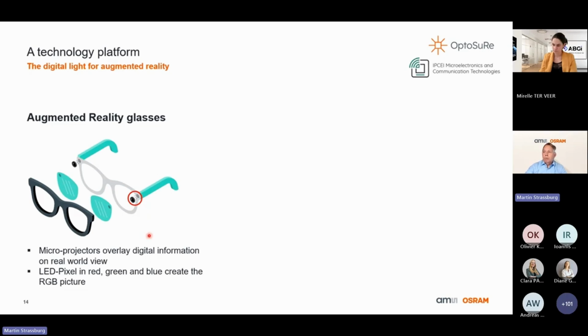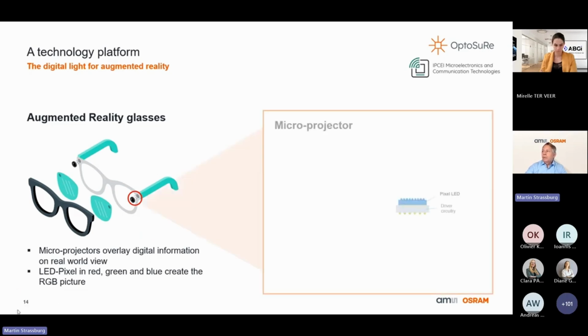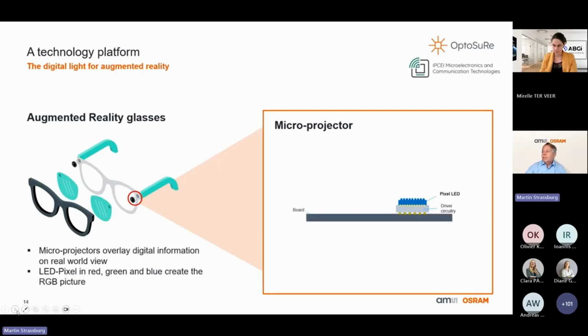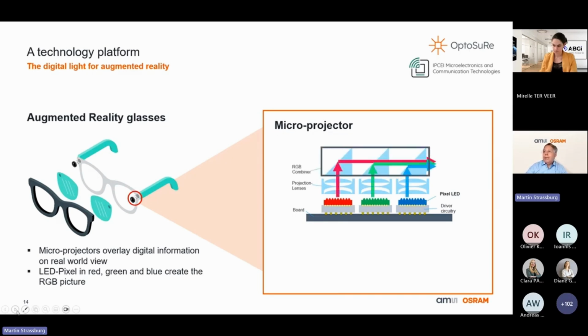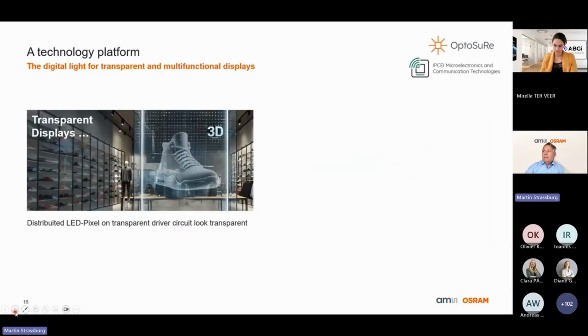The RGB projection is considered. And therefore we would use a micro projector. You see here again the micropixelated LED. Now 25,000 pixels are not sufficient anymore. Here we talk rather about 1 million pixels and smaller pixels. And to get the RGB, everything is put on a board. We have the red, green, and blue LED. This goes with projection and lenses, the emission of these arrays into an optical combiner, and this combiner is then coupled into the glasses. And the application of such micro projectors can also be different.